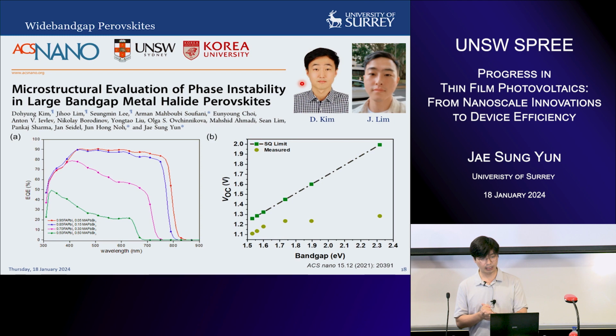So I have happened to work with a collaborator in Korea University, and we try to understand what happens in terms of microstructure for these wide bandgap perovskites. So we fabricated various wide bandgap perovskites from 1.55 eV, so these are narrow ones, and we made around 1.75 eV and 1.9 and 2.3. So we changed the bromide ratio, increase the bromide content. So if you can see, the efficiency deficit is definitely higher as you enlarge the band gap.